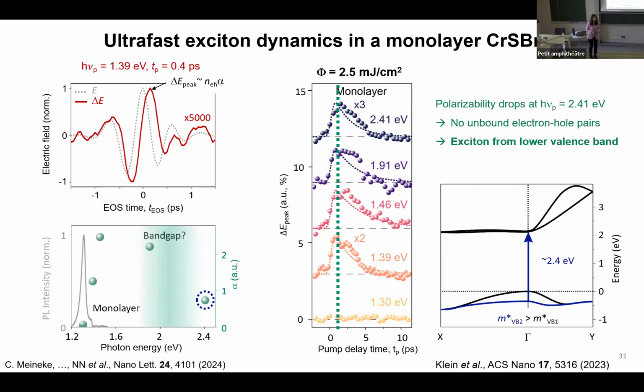So our terahertz nanoscopy experiment shows that the band gap of the monolayer should be for sure below 2.4 electron volts, because there we start forming another series of excitons.